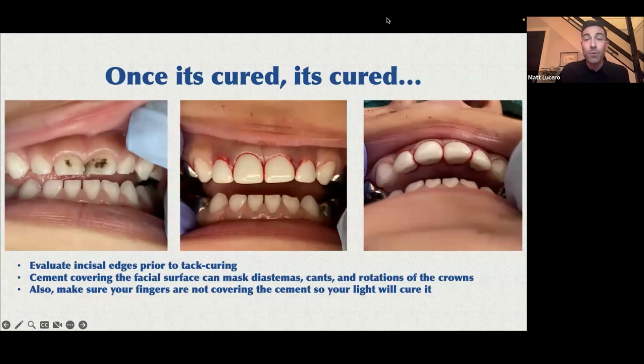One thing to keep in mind is that once it's cured, it's cured. So we can't move these crowns after we've locked them in place. And you can kind of see there where I learned a little lesson on keeping those crowns in the right spot. Pulled off my finger and I said, oh, darn it, we kind of made that rotated and now we're kind of set. But always keep in mind that once you cure these crowns, we can't really move them again. We have to be mindful of that.